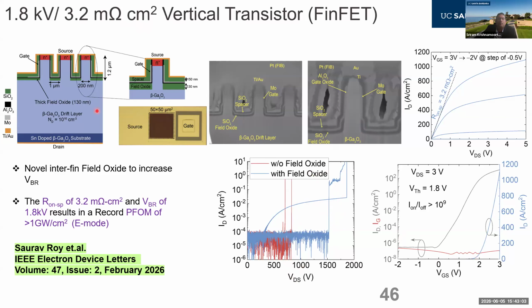Since we're working on bulk substrates, these devices actually have excellent on-off ratio. The off-state leakage current is pretty low. The on-off ratio is very good, 10 to the 9. And that's because we have the benefit of working on a very high quality crystalline substrate that nicely carries onto the epitaxial layer in terms of the quality.